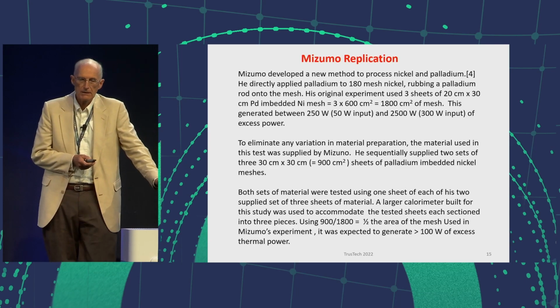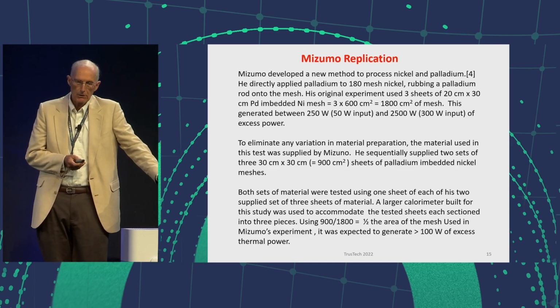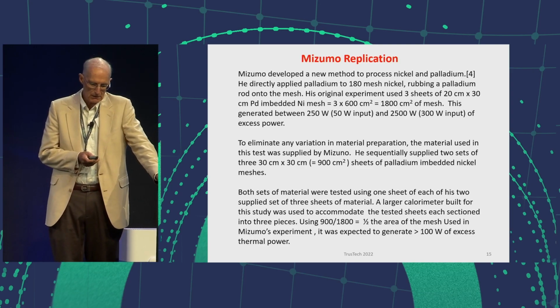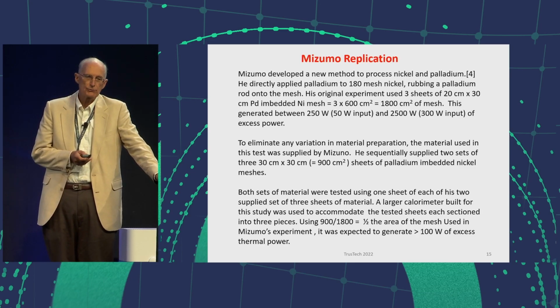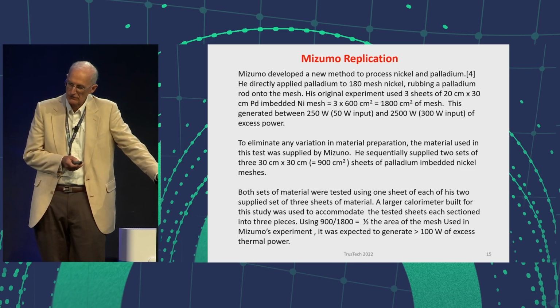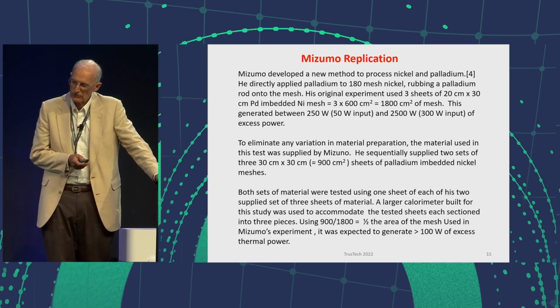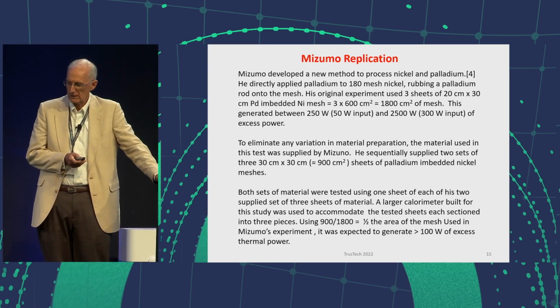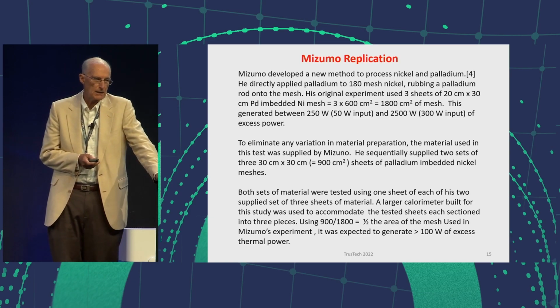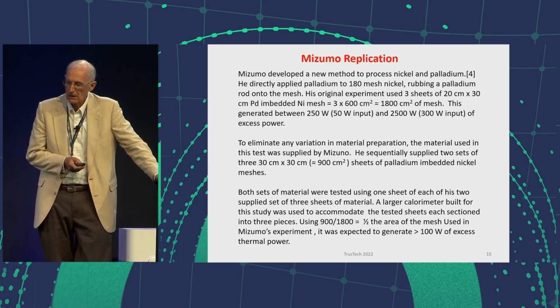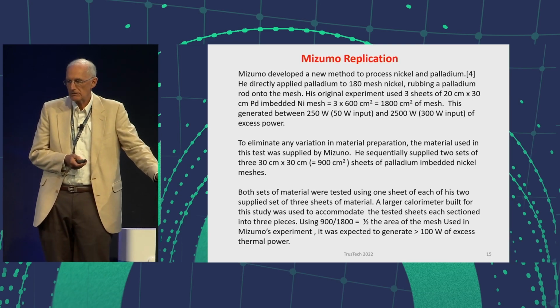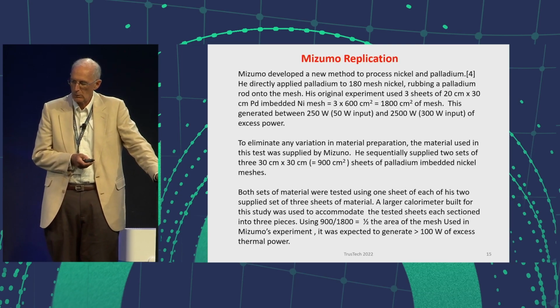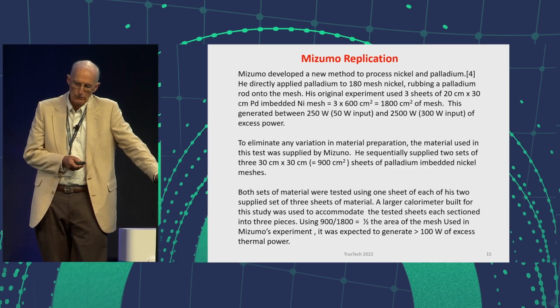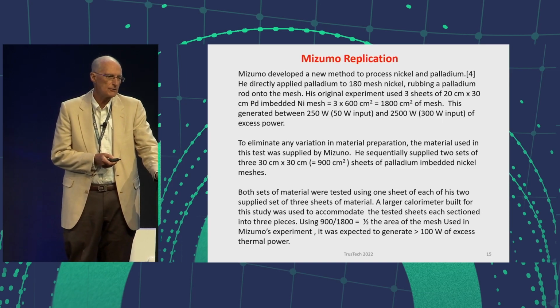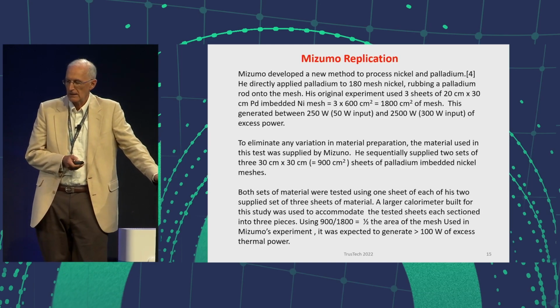And to eliminate any variations of this material, the material I studied was actually provided by Mizuno himself. He gave me 2 samples of treated material, which I used in 2 separate studies. I basically took 900 square centimeters of the material, and I cut it up into 3 strips and put it in a reactor. So if I got, say, his 250 watt result, I would expect something of 100 watts of excess heat in my experiment.